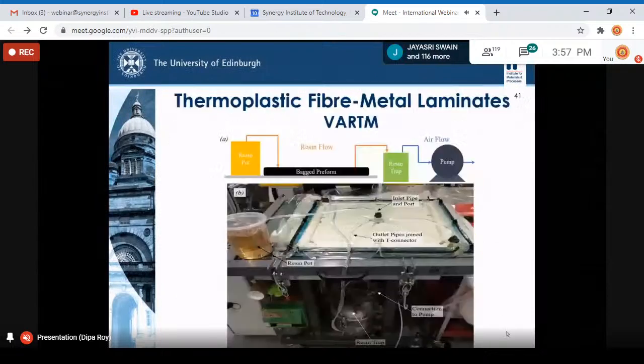And so with those surface treated alloys, we then manufactured by room temperature vacuum resin infusion, using the same technique that we used in the case of the glass fiber composite alone. And this was all done at room temperature. The aluminum alloy sheets had very fine holes so that the resin can permeate through the aluminum alloy sheets, and we can have the right wetting throughout the bulk of the composite.